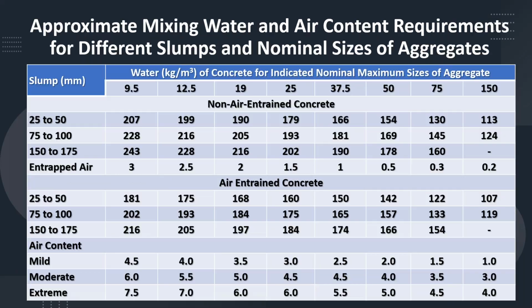Yeah, this is the main relation. This is from where we have considered. So if you see this ACI table, it has nothing to do with our own method. This entire set is the water content, for non-air-entrained concrete, and this is for air-entrained concrete. Now you see this particular row. This is the water content for the slump of 25 to 50, and this is the size of aggregate, 9.5 mm. We have approximated it to 10 mm.